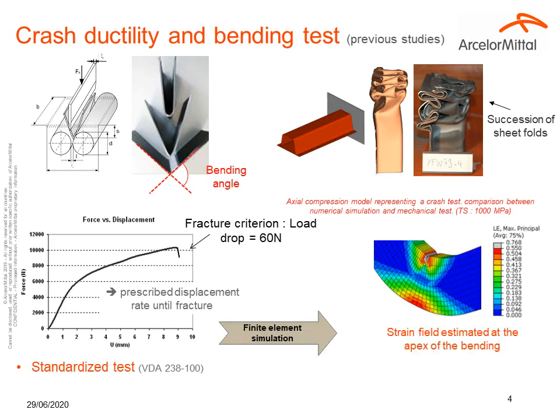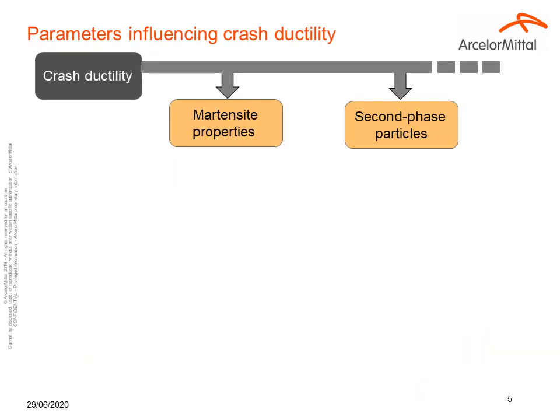You can then use finite element simulation to estimate the strain field at the apex of the bending sample. So to summarize, the bending angle at failure is determined experimentally. Then we can calculate the fracture strain in order to have an approximation of the crash ductility. This crash ductility can be influenced by several parameters. These parameters are, among others, the martensite properties and the presence of second phase particles.